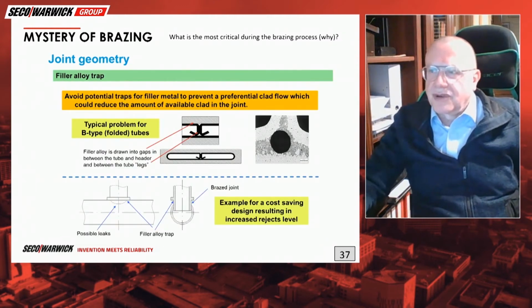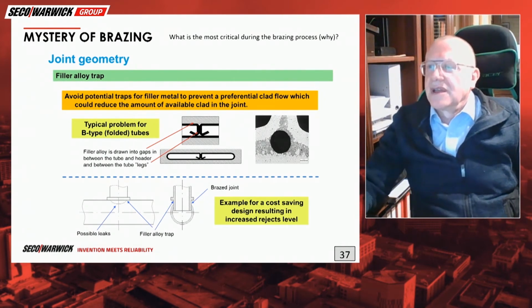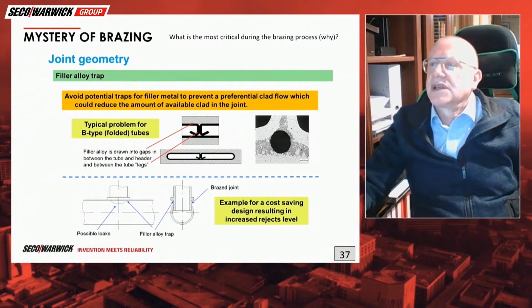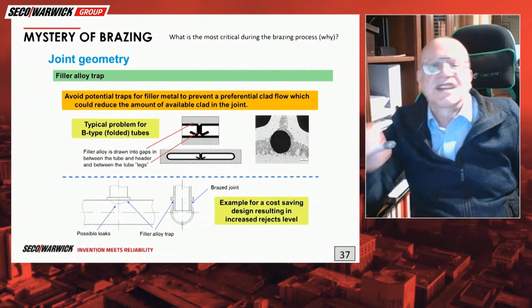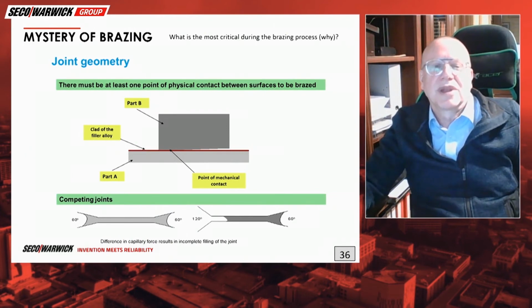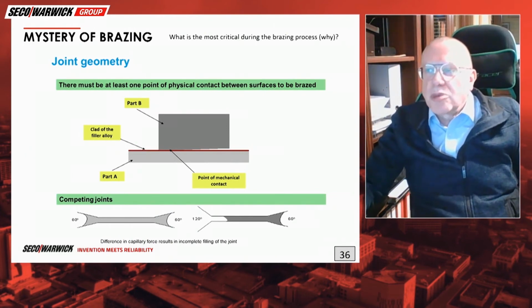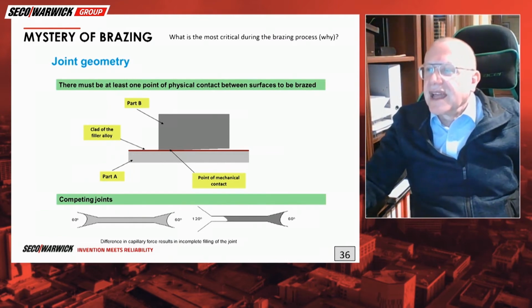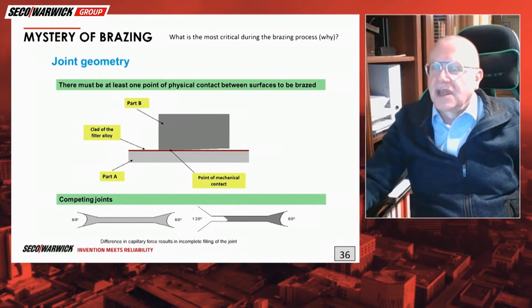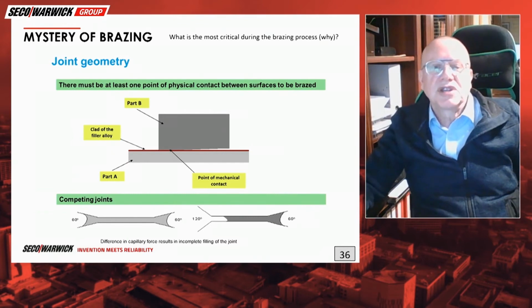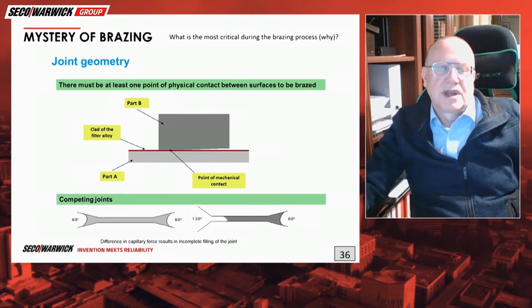Another important factor for designers is the so-called competing joints. A capillary force is a function of the gap between the parts, but also of the angle, which is shown here in this drawing. Actually, this is not the slide I want now. Sorry. Okay, this is the one below. A more open angle will create a smaller force to pull the metal into the end of the joint. Such a situation shows that we have so-called competing joints. Filler alloy will tend to flow to the right and not to the left. It's also very important when you design the parts. Please, next slide.